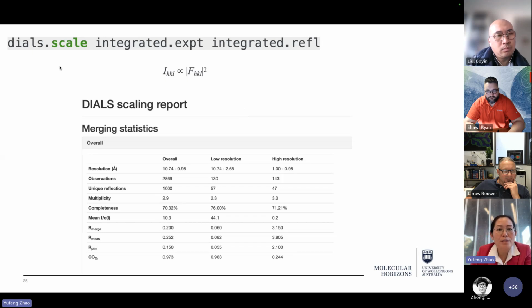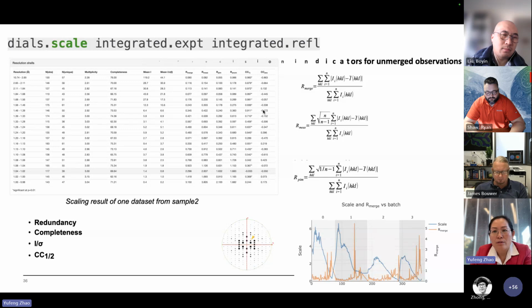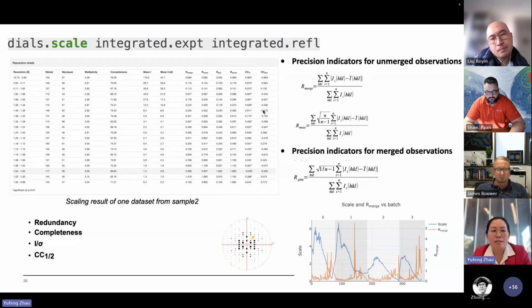In the scaling process, this program gives us a big report with all the statistical results from our data set. From here, we would pay attention to the multiplicity, completeness, signal over noise ratio, and all the R values, to give us an assessment of the deviation and the correlation coefficient. This step we normally process over and over to get the best result. I will normally go through every image.